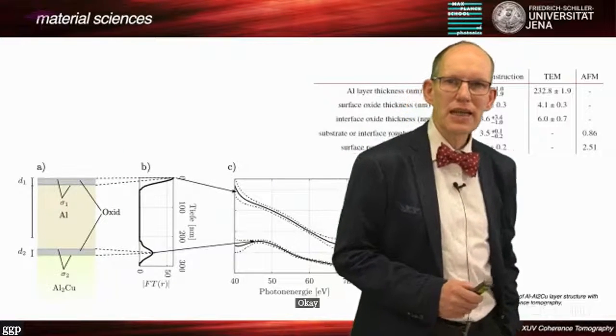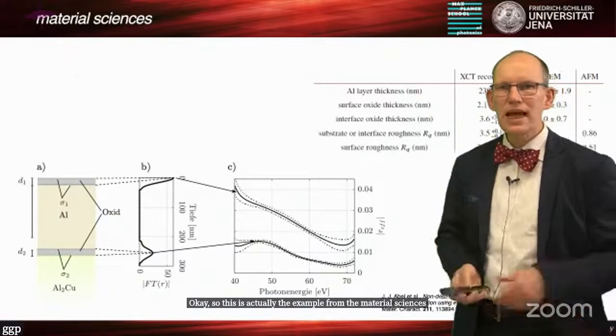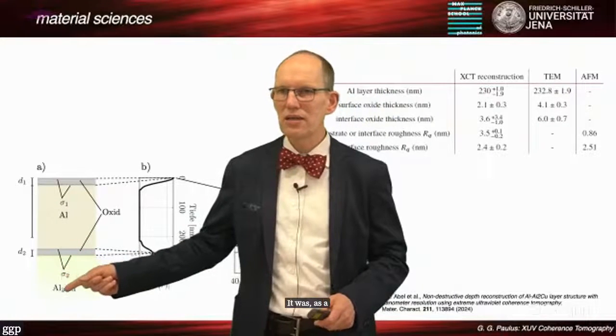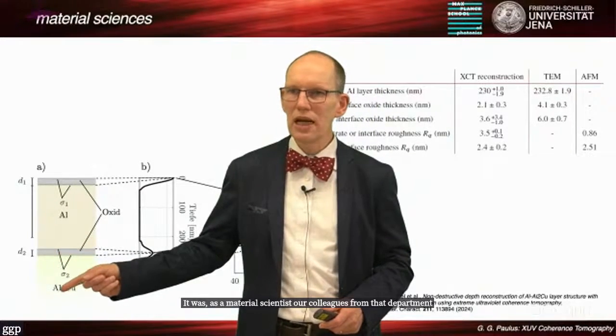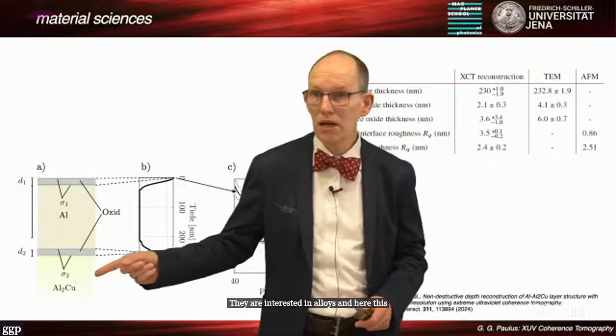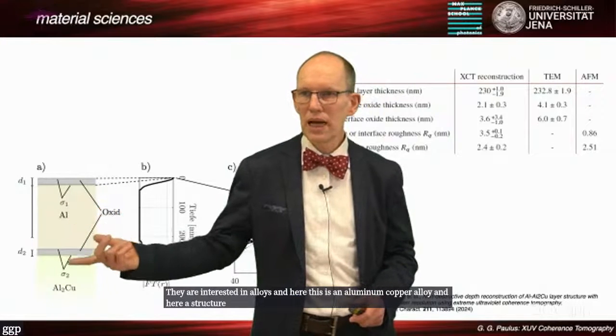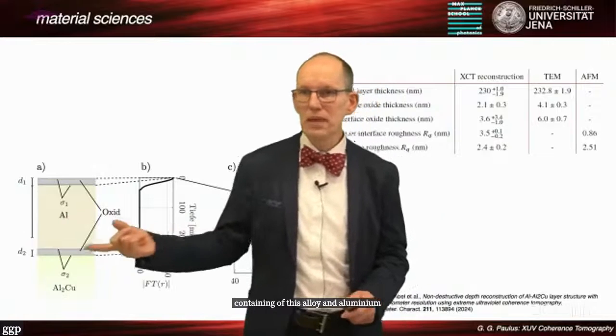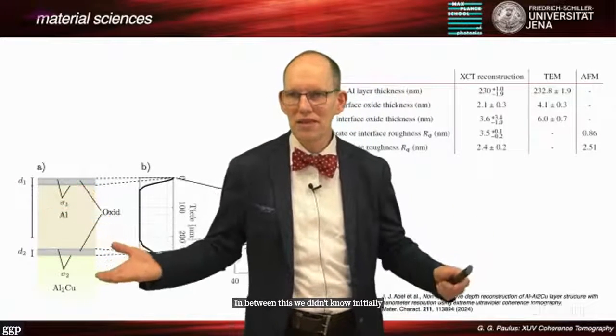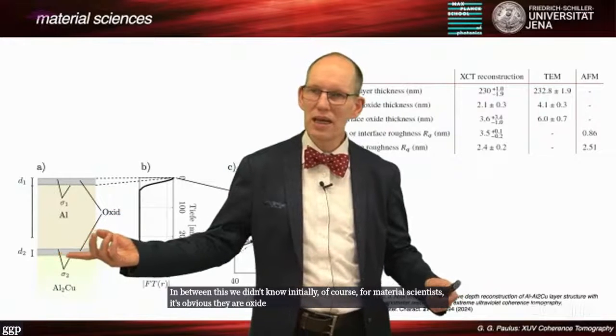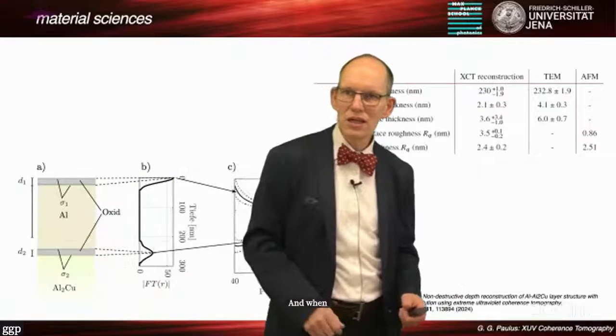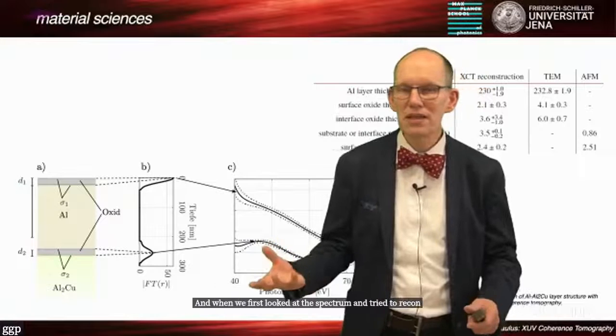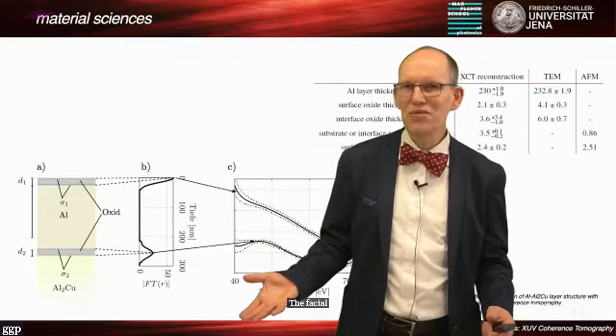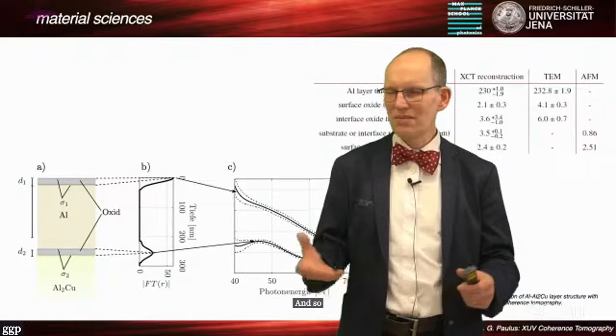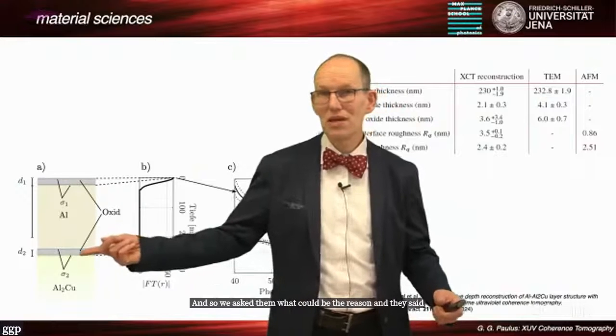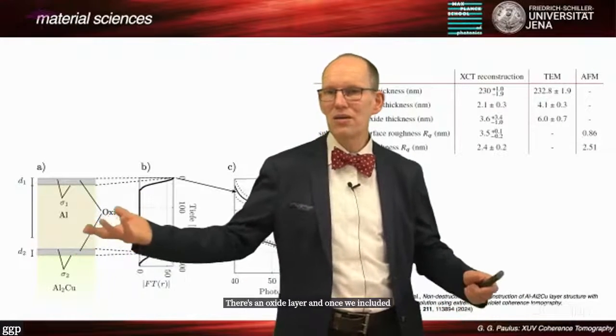Okay, so this is actually the example from the material sciences I referred to. Our colleagues from that department are interested in alloys. And here, this is an aluminum copper alloy, and here a structure consisting of this alloy and aluminum. In between, this we didn't know initially. Of course, for material scientists, it's obvious: they are oxide layers, very thin oxide layers, right? When we first looked at the spectrum and tried to reconstruct the phase, the reconstruction algorithm failed. So we asked them what could be the reason, and they said, of course, there's an oxide layer, and once we included that oxide layer, it converged immediately.